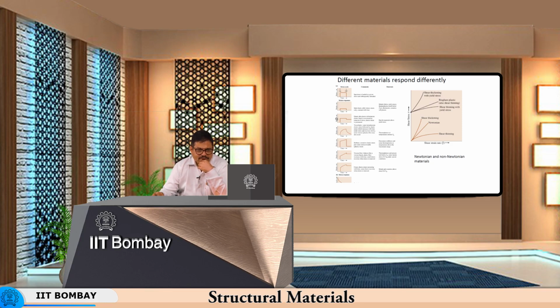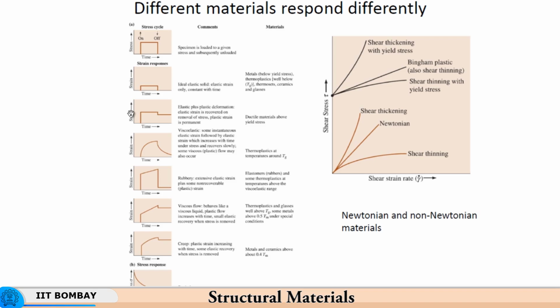So, as a result you have immediate increase in strain corresponding to the stress. Then there is an increase in the strain even under constant stress. So, even if the stress remains constant, the strain continues to increase. So, this is the difference between this and that, and then you have immediate drop in the strain as your load is removed or the stress is removed, but then there is a retention of some amount of strain, which is the plastic strain, which is non recoverable.